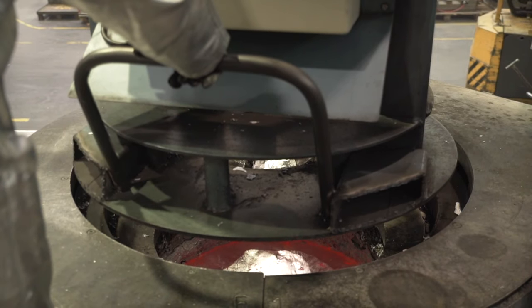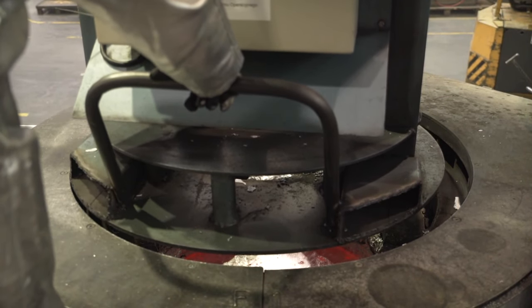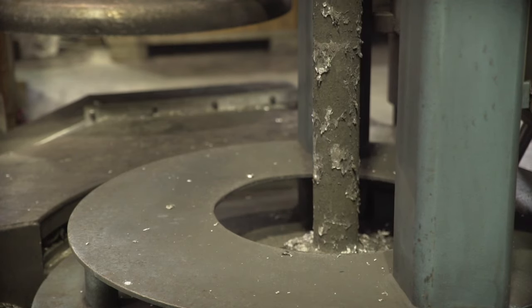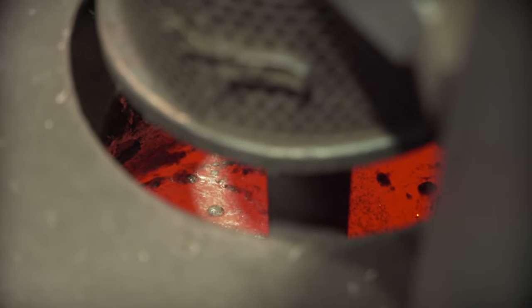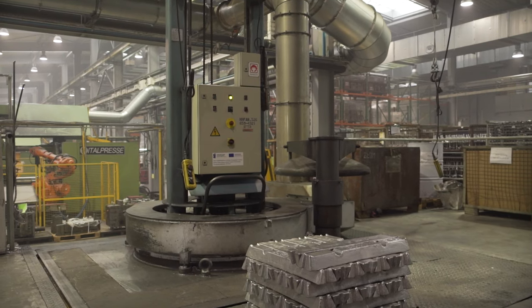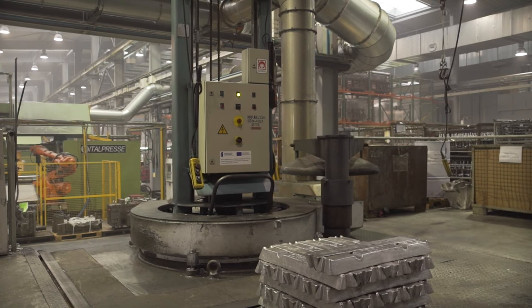The melted material is purified. The refiner is placed on top of the furnace, and its head, while rotating, administers argon to the metal treatment bath. Argon travels upwards, taking away all gases and contamination, which are then collected by the melter.